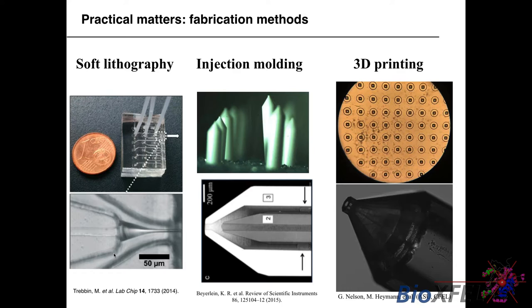One mass-production approach is soft lithography — a paper by Martin Trebbin, Henry Chapman and others shows how to stamp out nozzles once all design parameters are sorted out, though minimum feature size may not be as fine as needed for nanojets. Another approach is ceramic injection molding — some injection-molded nozzles made by the CFEL group are shown — which is good for making the outer component. The limitation is that you have to pull the mold out, so you're limited to converging geometries; the inner glass capillary still has to be made by hand.